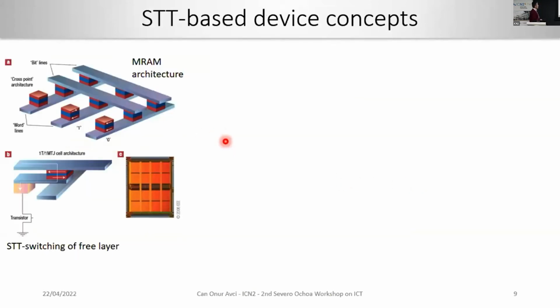So this kind of way of generating or manipulating magnetization has inspired some scientists to build a memory device called a magnetic random access memory. A magnetic random access memory, basically, it's an array of these tiny magnetic tunnel junctions where the information is stored in this magnetic orientation, and by adjusting the current passing through each of these layers, you can switch the magnetization, and also you can use a lower amount of current to read the magnetic data by using the effect of tunnel magnetoresistance. This is basically the tunnel counterpart of the GMR.